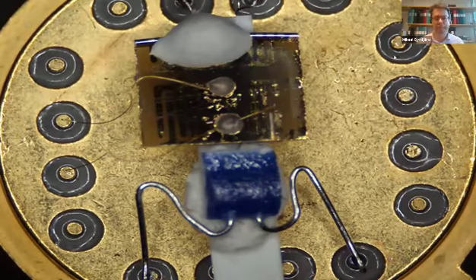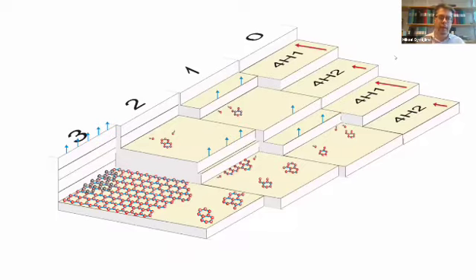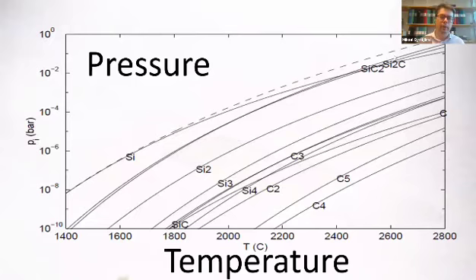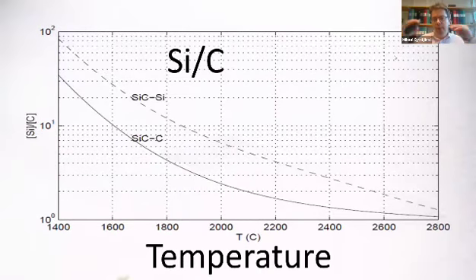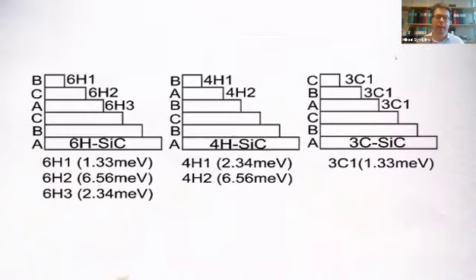And if we come back to this process of steps on the surface and the silicon and carbon leaving. Depending on the temperature, when you go up in temperature, there's a surface reconstruction. And then more silicon is leaving the surface due to different vapor species. And then the ratio of the silicon will differ depending on the temperature. So this is not very good for the growth if there's a big unbalance in the silicon to carbon ratio. But this can also be used for making the graphene. But also here you have a surface reconstruction which is happening. And this happens on the different silicon carbide polytypes, and you have different steps, different terminations of these ones.